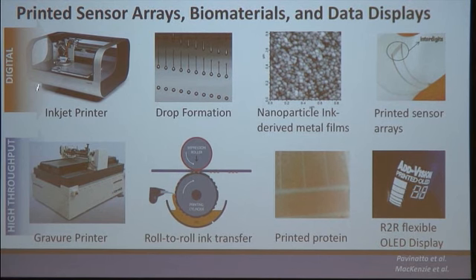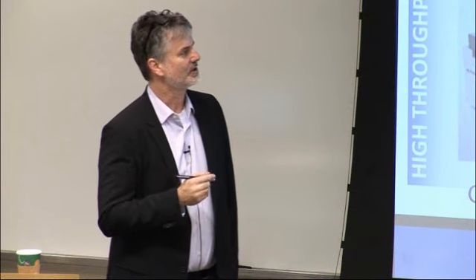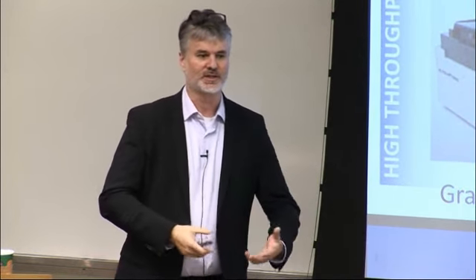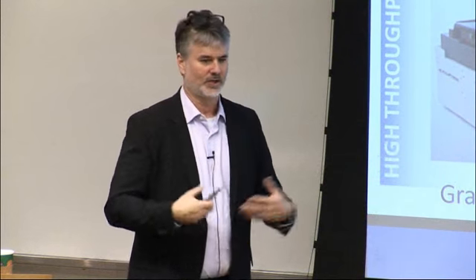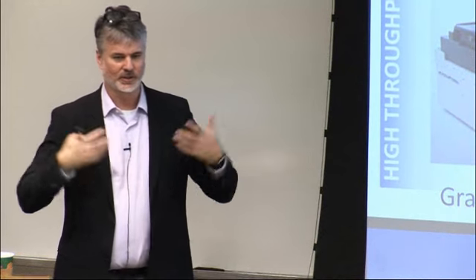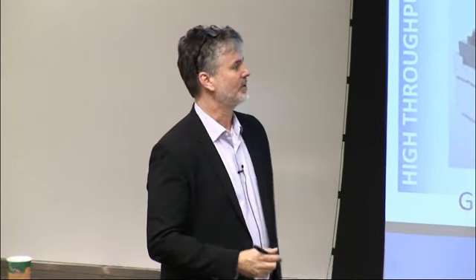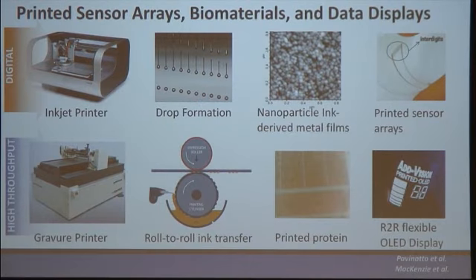There was a lot of work in the deposition systems, but a lot of the hard work has focused on materials development, to produce materials that end up as functional. In this case, this is a nanoparticle silver that started off as silver nanoparticles dispersed in an organic solvent, maybe 4 nanometer, 10 nanometer nanocrystallites. Those are small enough that they're dispersible into a solution like dissolving salt in water. They're so small that the molecular forces can disperse them, and now we can use that as an ink and run it through a printer. Once we get it on the substrate, we dry it, but we don't have a metal yet. We have to sinter that metal and actually grow those crystallites and turn it back into a continuous metal. A lot of engineering over the last 10 years has gone into that.